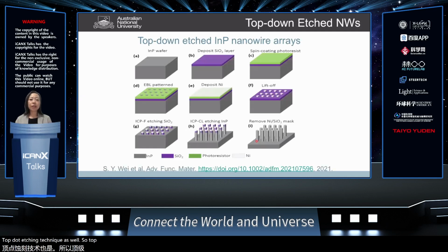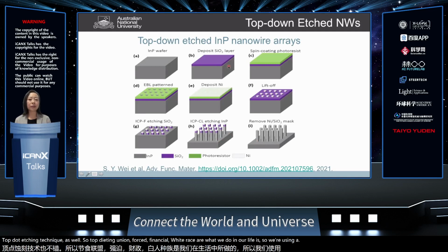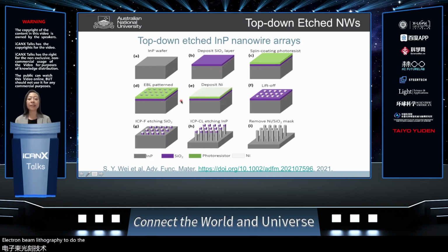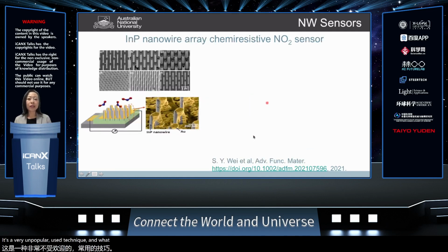For the top-down etched indium phosphide nanowire array, what we do in our lab is use silicon dioxide as well as nickel as the mask. We use electron beam lithography to do the patterning, and then we do ICP etching to create this nanowire array. It's a very commonly used technique. What we're trying to do is use the interesting conductivity change of the indium phosphide nanowires for gas sensing.